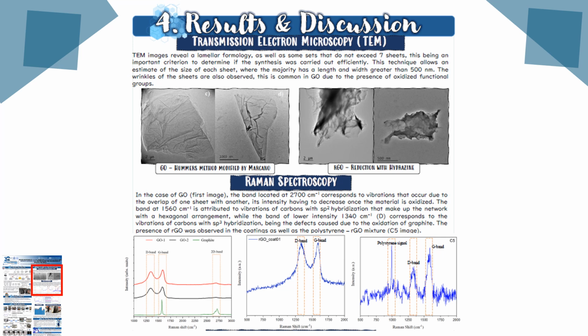On the left, we see the most noticeable differences between GO and graphite, including the formation of the D band, which is attributed to defects in the sheet, and the broadening of the G band, which is related to the carbon double bonds.